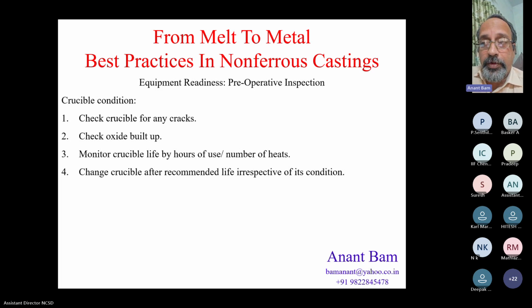Then monitor the crucible life by hours of use or number of heats. Change the crucible after recommended life, irrespective of its condition. Because if the crucible cracks or fails during operation, then it becomes a very big mess to clean the furnace. It may invite short circuit. It may invite accidental shocks to the operator. And the repairs or the damages of a broken crucible during operation take a few days. Instead of that, if the recommended lifespan is over, on a weekly off, just change the crucible even if it is apparently good or it is looking good in working condition. That will prevent all these pitfalls, and it's again a TPM activity. Next slide, please.